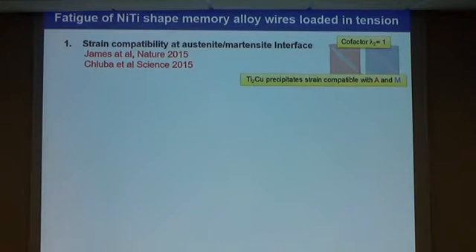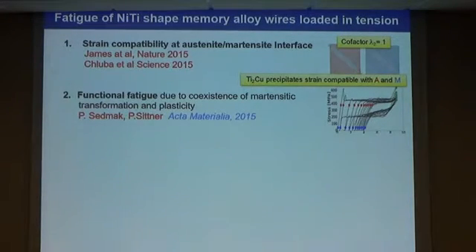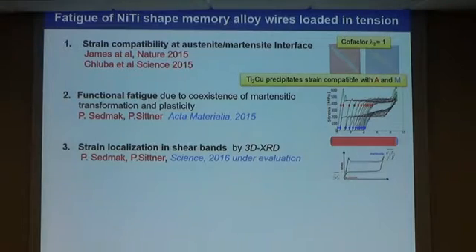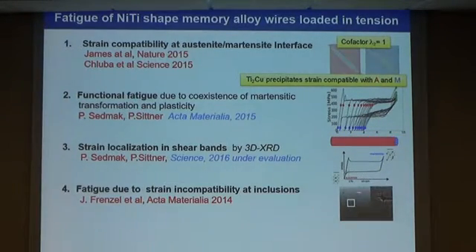This is basically the idea which is in this Chluba's paper, which means that if this is solved, probably it would work. But still, in real wires with grains, you will have these kind of things and residual stresses, so we need to understand these things as well. Wire in tension will not deform homogeneously, but will deform in this way, and here there is a strain change up to 6 or 7 or even more %, so we need to understand this localized behavior because it's very difficult to get rid of that. And finally we have here the inclusions, and the cracks always start at the inclusions, so at first if we want to do something we have to get rid of the inclusions.